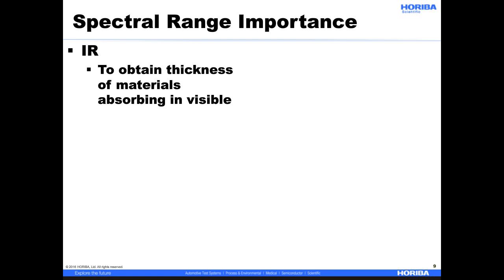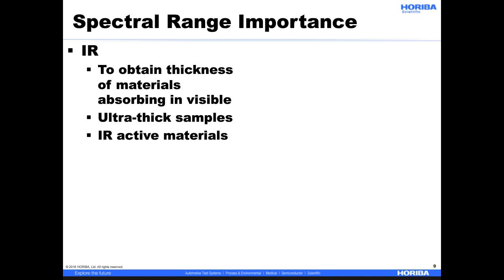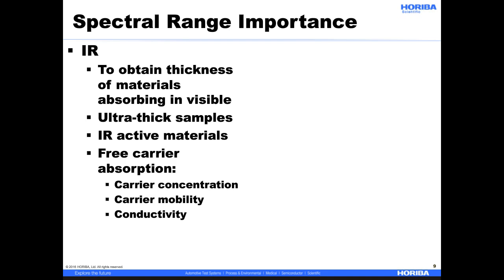As far as the IR, this is to obtain thicknesses of materials absorbing in the visible. It's also for ultra-thick samples. In the IR, you'll see many more interference fringes, and you'll have good resolution for the interference fringes. It's good for IR active materials and free carrier absorption, so you can obtain carrier concentration, carrier mobility, and conductivity.